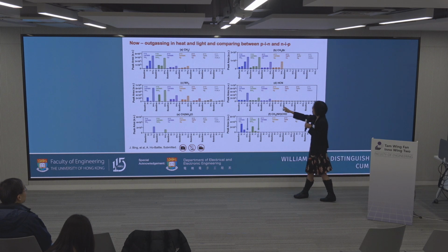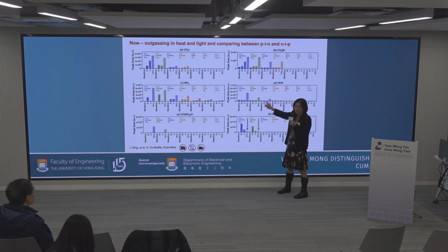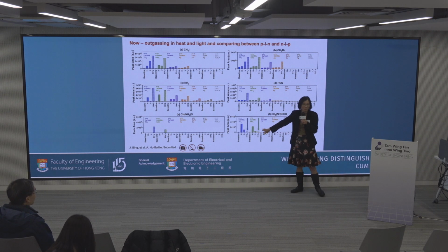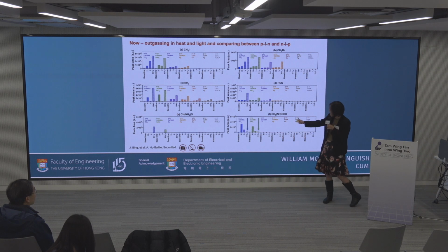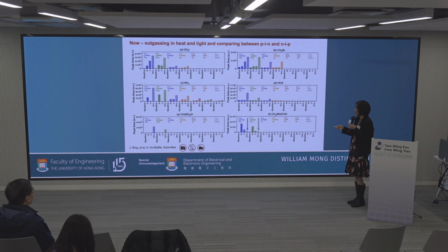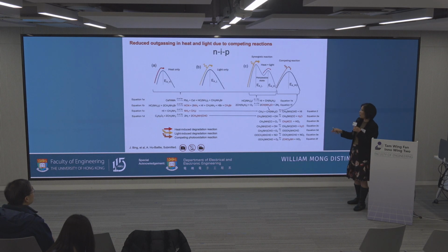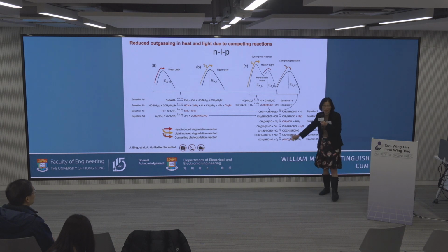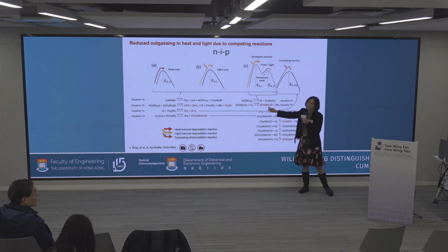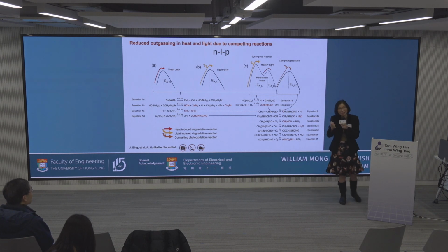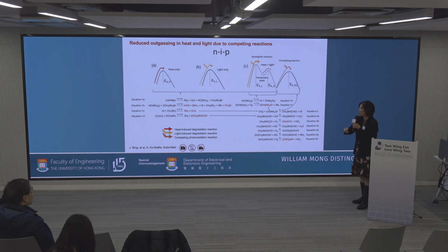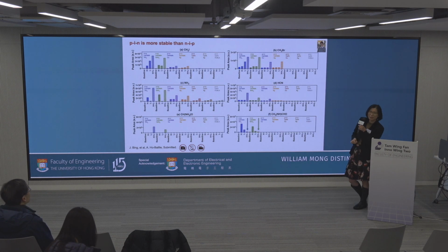So what can we see here? Well, if you have heat and light, it makes the outgassing worse. But in this case, when you have heat and light, that outgassing is reduced. Why is it the case? It's because only in NIP, when you have the light stress, you have a whole bunch of other reactions that compete with this product. So they're actually competing. They're using that to drive other decomposition. And that doesn't happen in PIN.